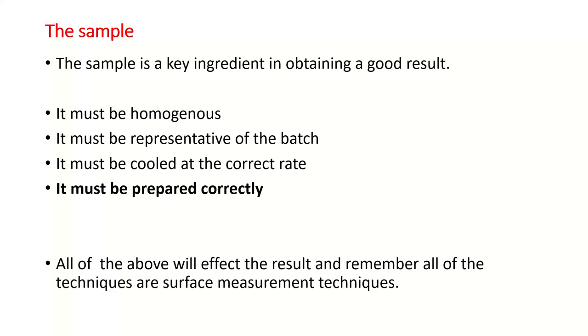If your sample is not homogeneous, then obviously your repeatability is going to be out. You're not going to be able to get the same result every time you spark or every time you test. So make sure that your sample is a good mix. In a lot of cases, I've seen additions put into furnaces and the sample's been taken too quickly, so it's not had a chance to actually mix before the sample's been taken. It must be representative of the batch, obviously, depending on whether or not it is a molten sample or whether it's a batch of incoming stock. Are you going to do one or two, or are you going to do all of them?